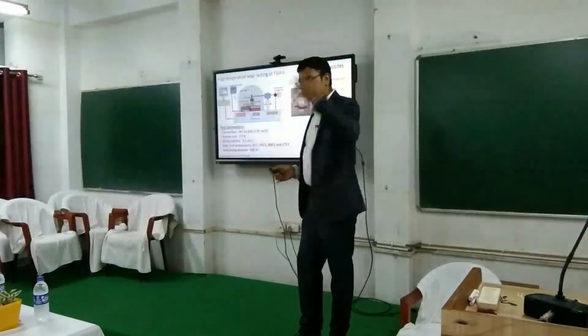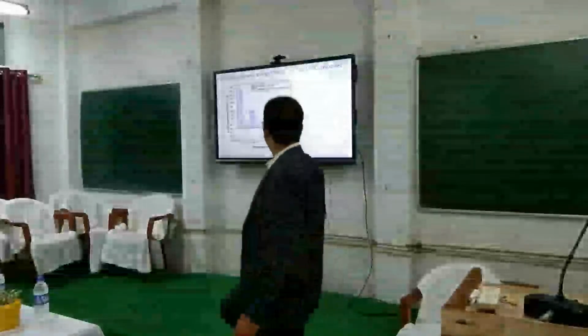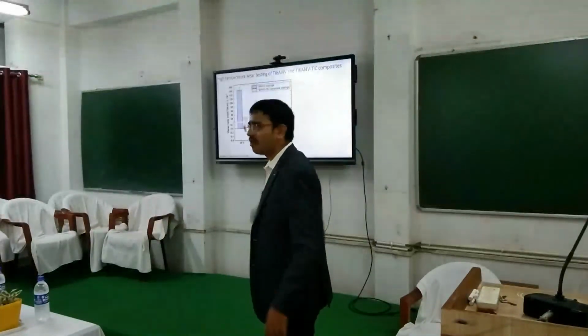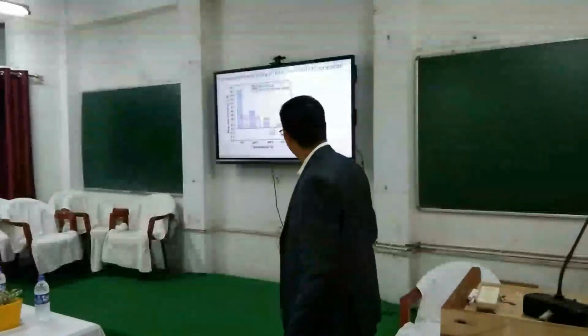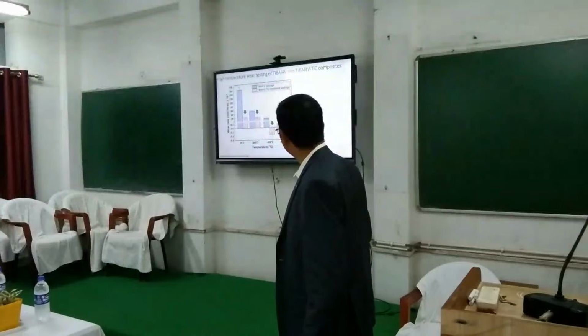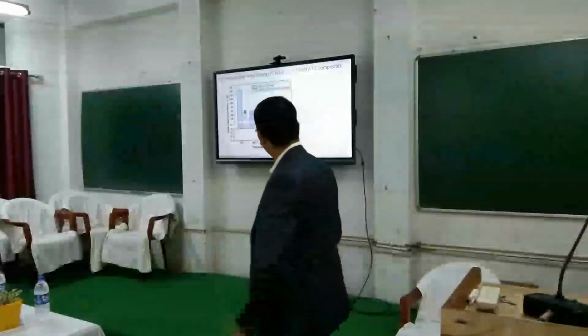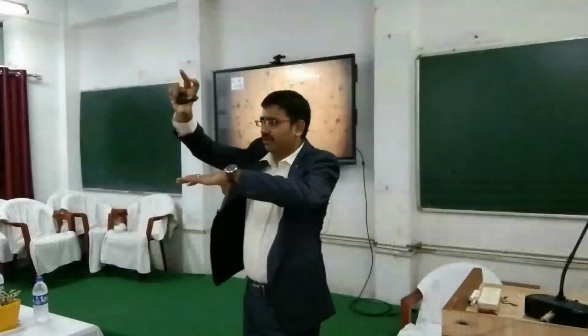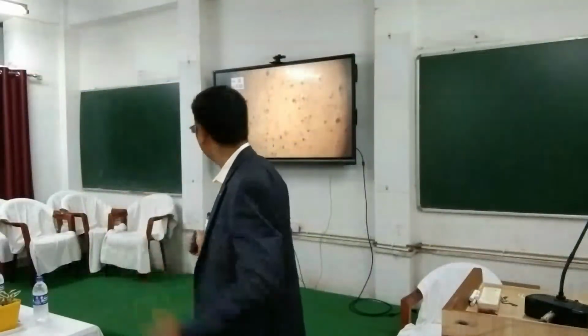And that's why your nascent coating is getting protected and the wear rate is coming down. So we also did tests at high temperatures, and even at high temperatures we found that composite coatings actually perform better due to glaze layer formation and all. Due to lack of time I will not discuss that. And one thing we can observe is we had the chance to do some in situ tests. That is, you mount a microscope, use a transparent ball, okay, and measure how the friction is changing with respect to cycles. So I don't know if it will play.